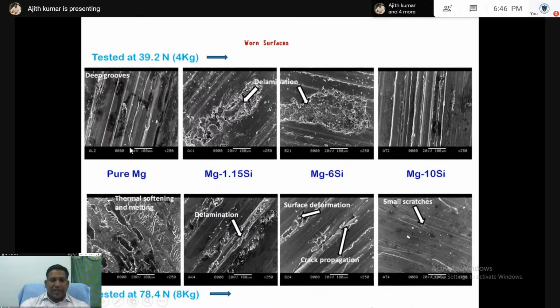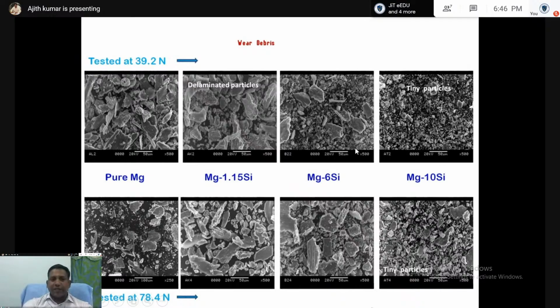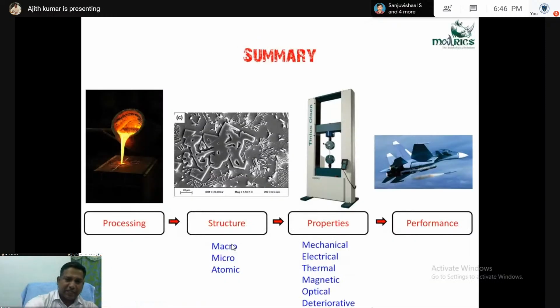From that, we can understand that in pure magnesium, deep grooves are there. That is due to thermal softening and melting. This mechanism is thermal softening and melting. And in magnesium 1.15 Si and 6 Si, you see there are delaminated type of spaces. At the same time, the debris also looks like delaminated particles. So we understood that this kind of wear is delamination wear.